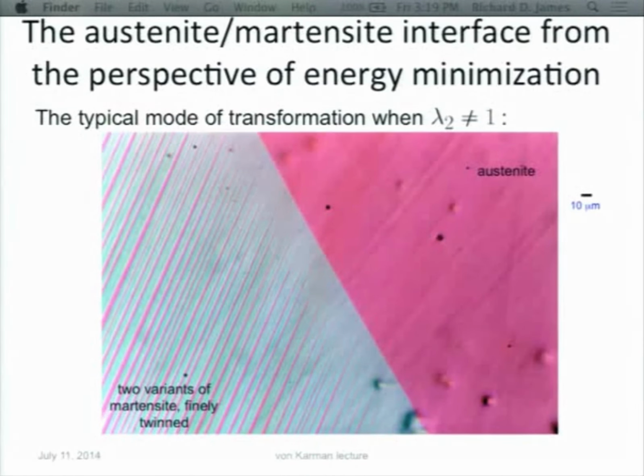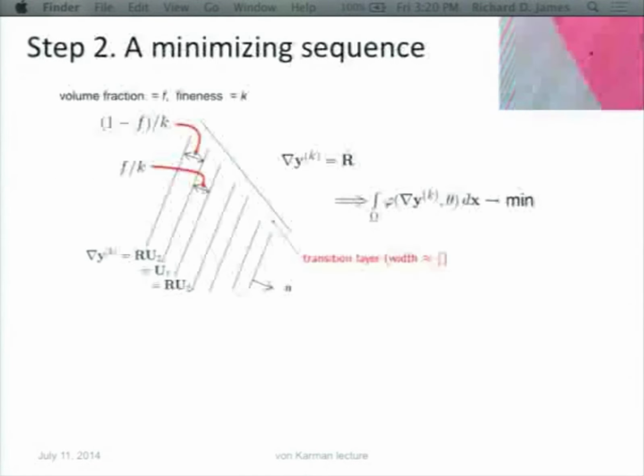Okay, there's a small interfacial energy on each of the boundaries of those bands, which is not taken into account by this calculation. As you make the bands finer and finer, of course, the total interfacial area, the total interfacial energy gets larger and larger. And so somehow this should compensate for the bulk energy, which can be made to go to 0 by allowing the twins to be finer and finer, allowing these bands to be finer and finer. So that's the explanation. And there's further models which take that into account.